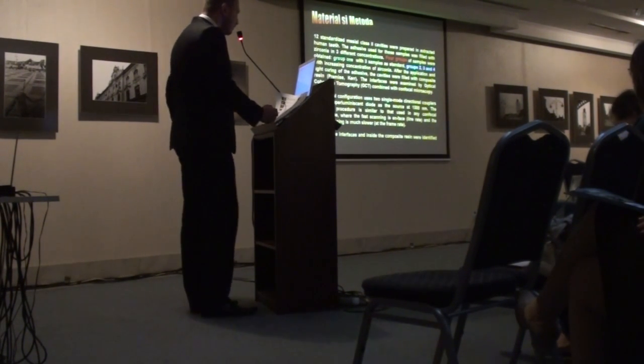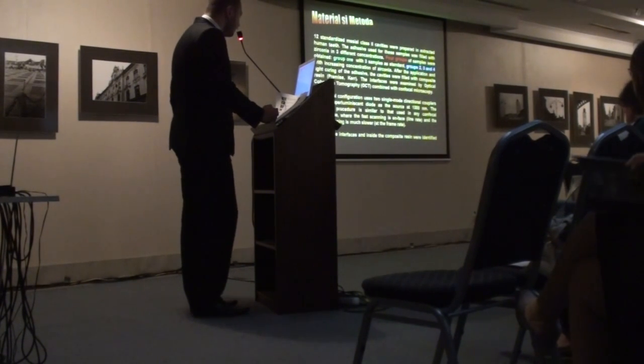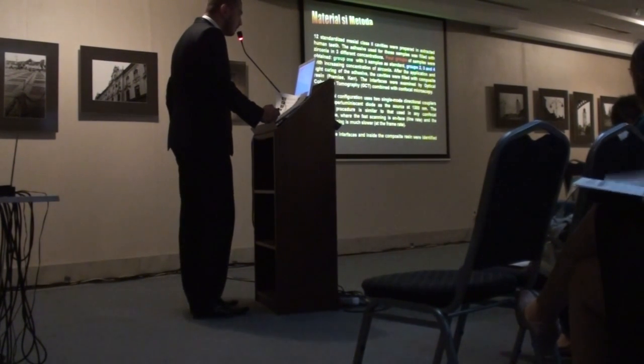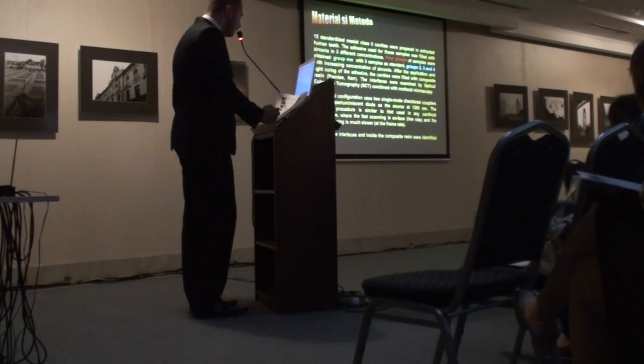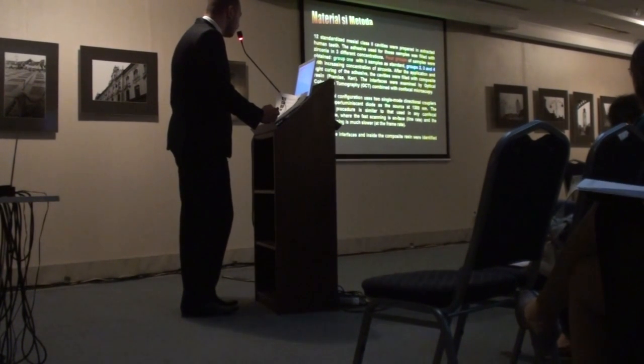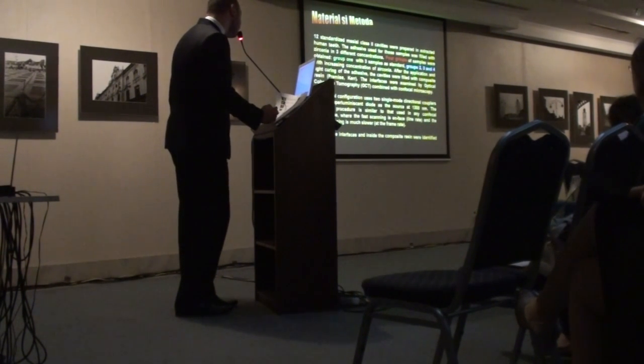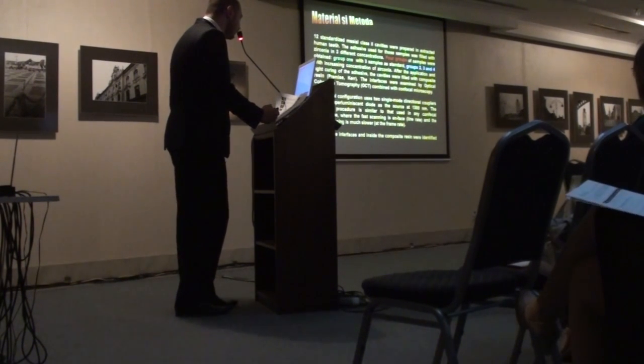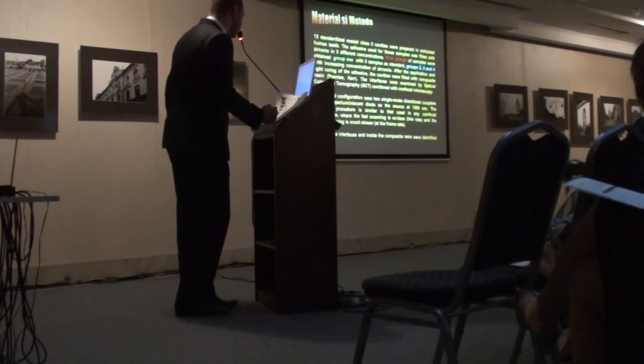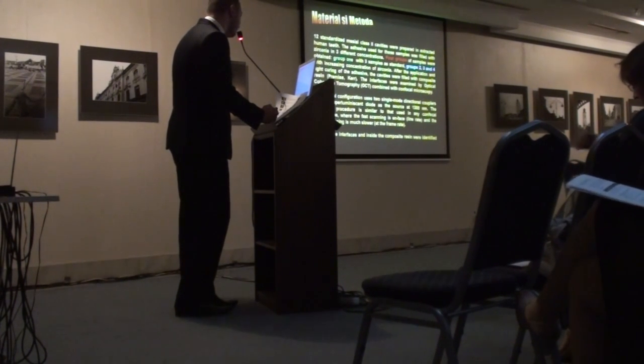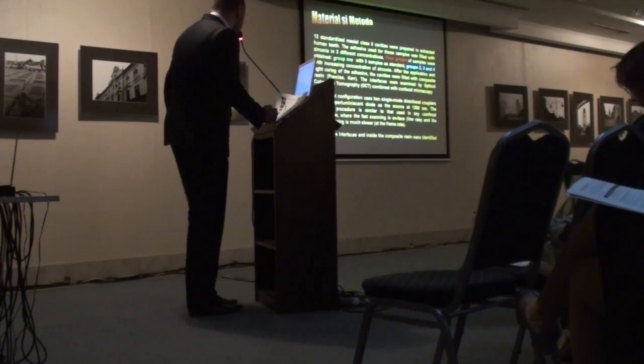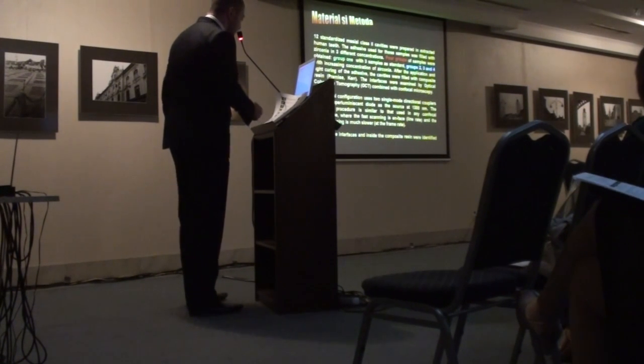The interfaces were examined by optical coherence tomography, OCT, combined with confocal microscopy. The optical configuration uses 2 single-mode directional couplers with a superluminescent diode as source at 1300 nanometers. The scanning procedure is similar to that used in any confocal microscope, where the fast scan is the line rate and the depth scanning is much slower at the frame rate. Gaps at the interfaces and inside the composite resin were identified as well.